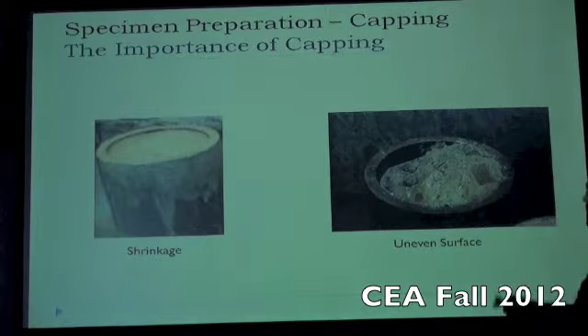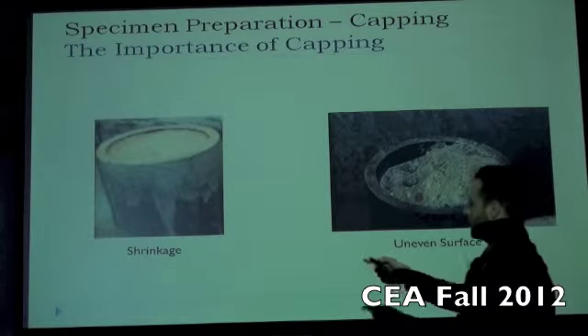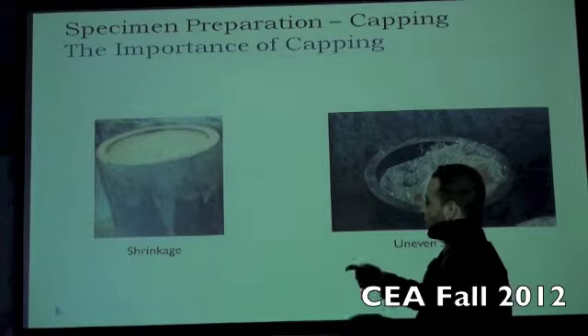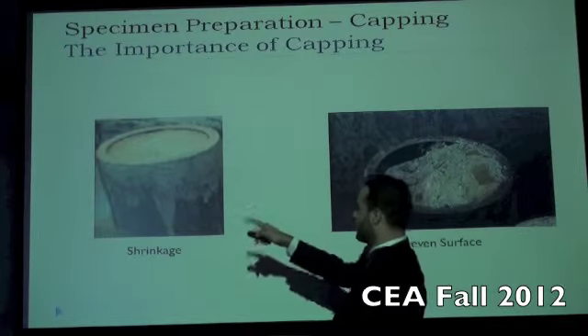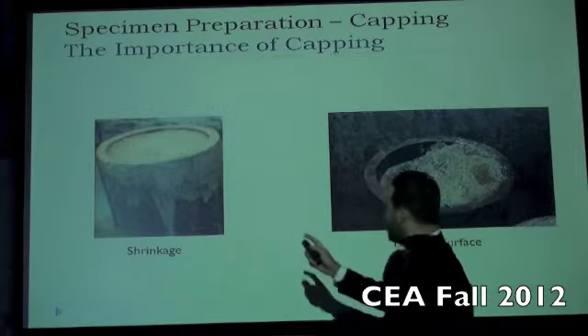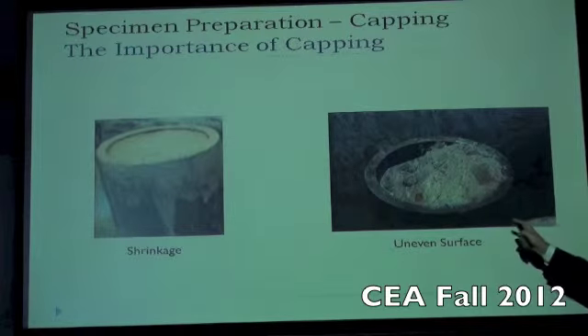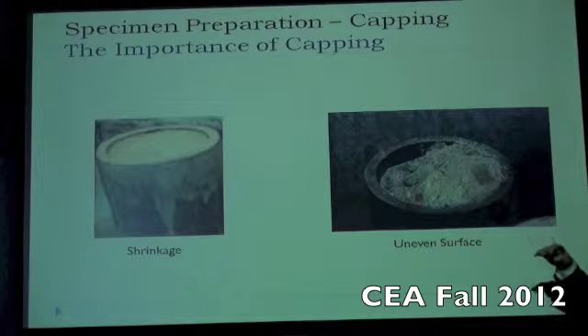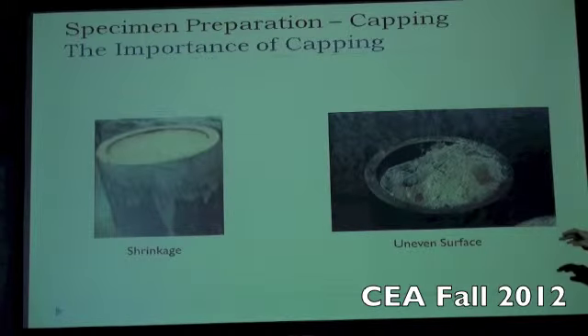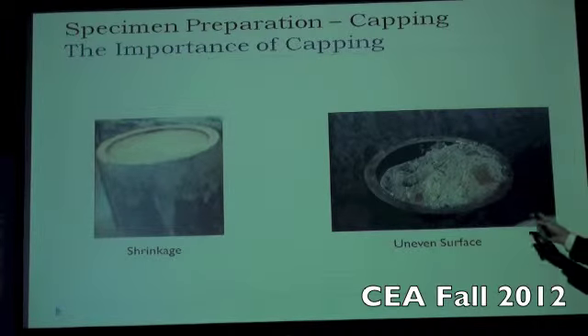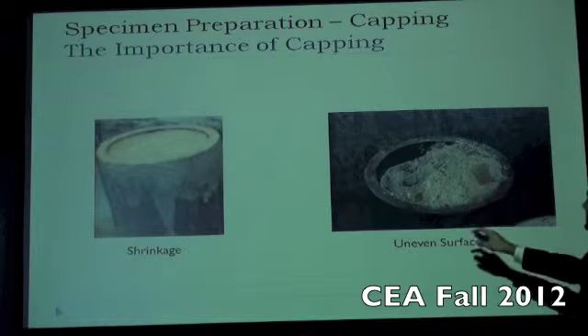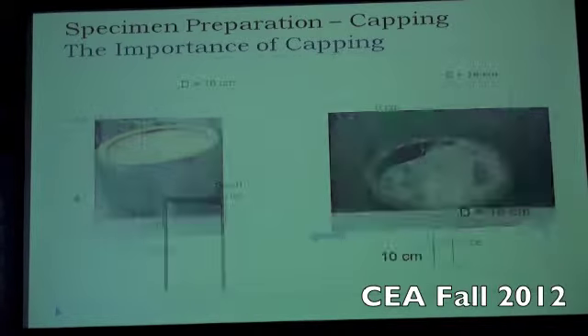As I said before, we had some problems after filling the tubes with concrete. One problem is shrinkage: the surface of the concrete decreases below the surface of the pipe itself. And this is a result of using the steel end cap at first, because when we took out the pipe, some of the concrete stayed in the steel and didn't come out. So we had a surface that is not very flat, and it's not a good result. That's why we are going to do capping.